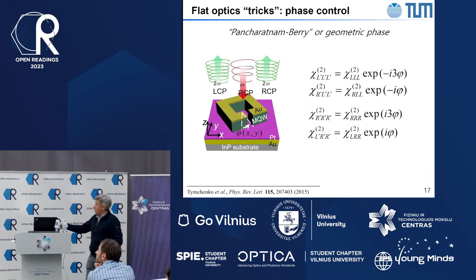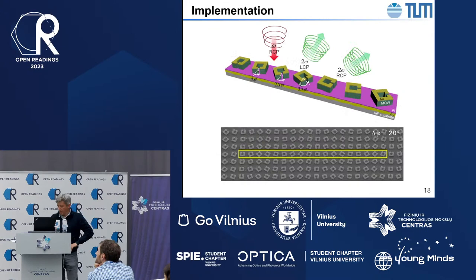For left circularly polarized light input and left circularly polarized output, a unit of rotation corresponds to 3 times change in the phase. And for the right circularly polarized output and left circularly polarized input, this rotation corresponds to once change of the phase. This follows from some mathematical considerations. But basically, both this and that will have a phase gradient. Now we can fabricate this and test if this phase gradient holds true.